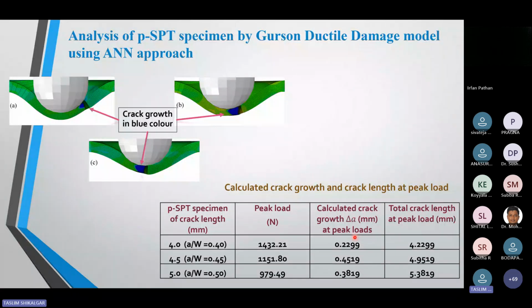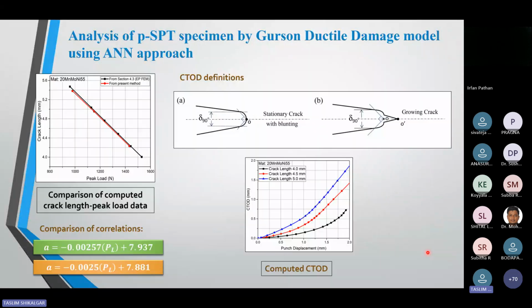Initially I developed these linear correlations without the damage mechanics model. Now I developed similar correlations with the help of the damage mechanics model. So here I got this clear idea: I am getting the same results from the damage mechanics model also.